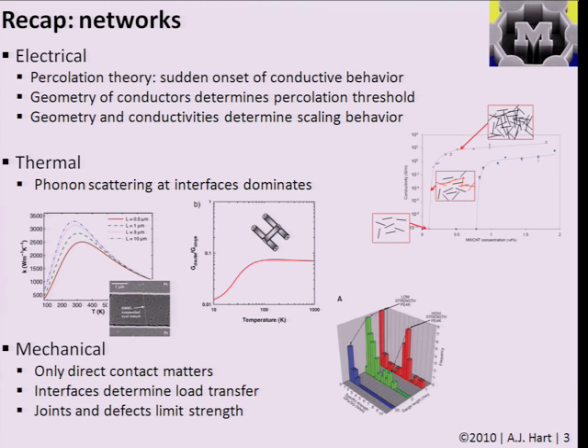We also briefly talked about mechanical properties, thinking of nanostructures as networks of springs. Unlike electrical and thermal properties where tunneling or vibration communication across gaps matters, in the mechanical case it's really the physical connection of the structures that matters. When we looked at production of threads or yarns out of carbon nanotubes, we saw limiting cases: very high strength when pulling on many continuous nanotubes in parallel, and much lower strength over longer distances where strength was dominated by the strength of interconnections among the tubes.